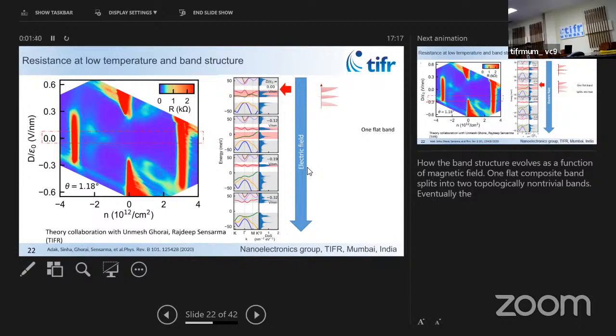How do I know the twist angle disorder? Ideally, the way to know twist angle disorder, this is the terminology, is by imaging using STM or a technique called piezo response force microscopy. But in these devices which are sandwiched, we don't have access to the inside. But what we have access to is called the moiré peak. If I plot the resistance through the middle, as in the dashed rectangle, I will see a moiré peak like this.